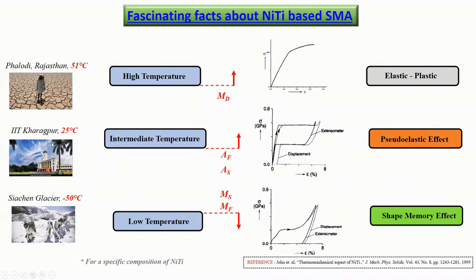Whereas if we use it at intermediate temperature, we can see some pseudo-elastic behavior, where it deforms elastically up to a certain extent, and then shows a strain plateau, following which if we unload, it comes back to the initial shape. Unlike the regular elastic plastic one, this kind of behavior is known as the pseudoelastic effect, whereas at low temperature, we can still have some kind of hysteresis, and this is related to the shape memory effect.